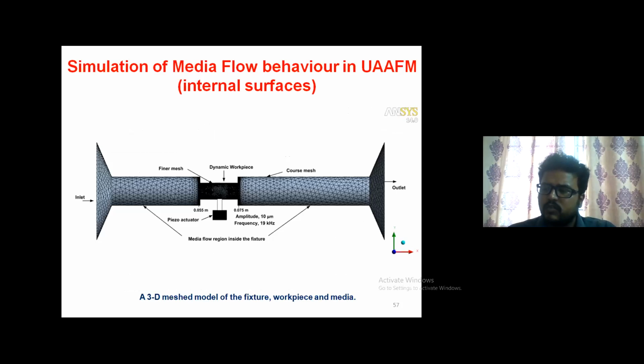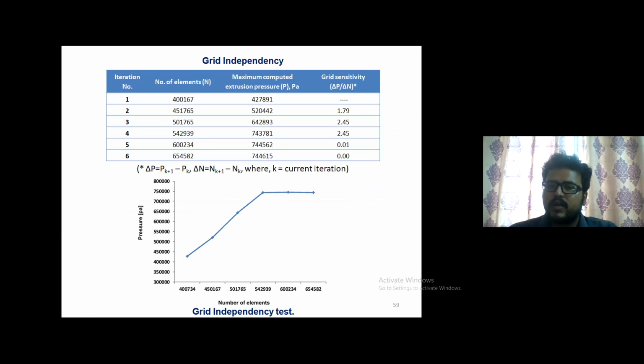So we have done a few simulation studies also before fixing the parameters. In the simulation studies, we found that the amplitude which is applied in the ultrasonic abrasive flow machine does not have any influence. So we fixed amplitude as a constant 10 micrometer, and we varied frequency. We also observed from the simulation that the variation of frequency is giving a better result. Before doing experimentation, we applied simulations using ANSYS Fluent, and we observed that by varying the frequency, there is a lot of improvement in the response. So from simulation also, you can screen a few factors. Like in my case, I fix the amplitude, I am not varying the amplitude, and I am varying the frequency.